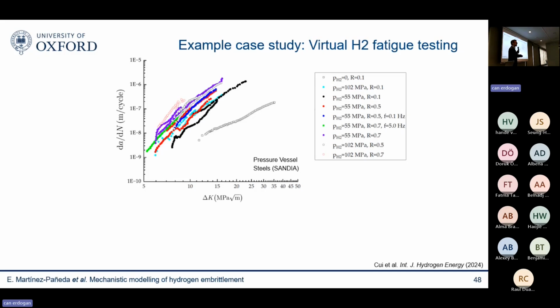pressures, up to 100 megapascals of hydrogen pressure, and different load ratios and different frequencies. And this data is very, very valuable. This is what engineers are using these days to design hydrogen energy infrastructure. But it's also very difficult to get. There are only, I would say, 5 labs in the entire world that are able to run experiments at these pressures and cyclic load. So it's expensive and very difficult to get. It's quite a challenge to run experiments at 100 megapascals of hydrogen pressure.